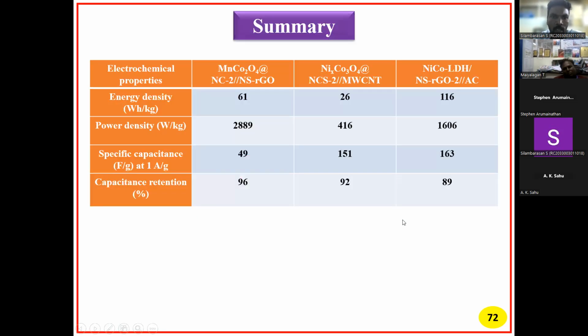Next, summary and future work. In summary, overall, MnCo2O4 with nitrogen doped carbon, nickel doped cobalt oxide with nitrogen doped carbon, and nickel cobalt LDH composite with NSRGO. Here the nickel cobalt LDH gives more performance compared to the others. It has a higher energy density of 116 and a power density also of 1,606. The specific capacitance in the 2 electrode system is 163 and the capacitance retention is 89%.